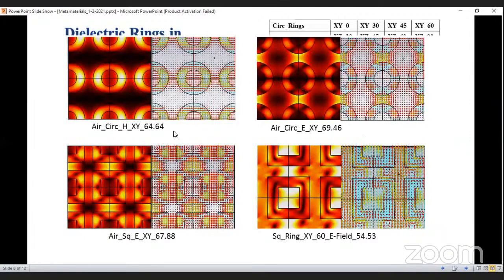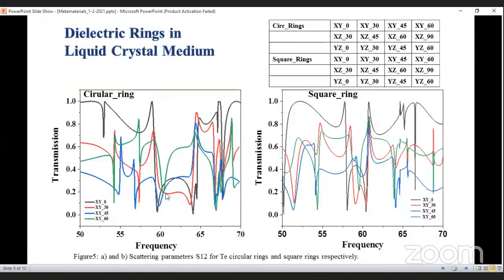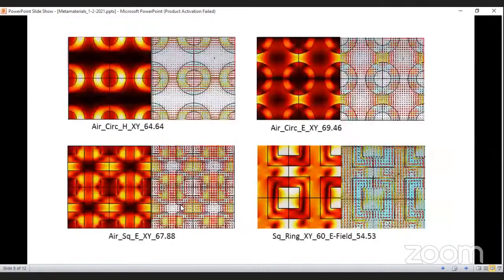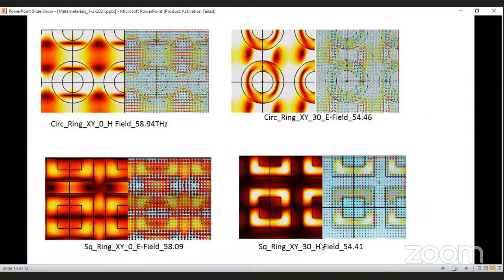Just by changing the liquid crystal angles, we found that at some angles some resonance modes are displaced or enhanced. This is one characteristic which we observe here. We observe modes like electric dipole, octopole, and quadrupole in air as well as in square rings in liquid crystal mediums. To obtain the details of these magnetic and electric modes at excited resonance, we need to do some work in detail. So this is our future work.